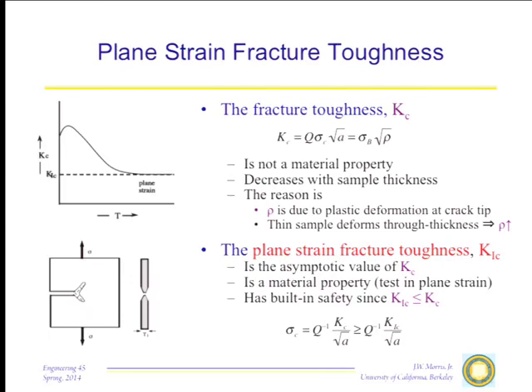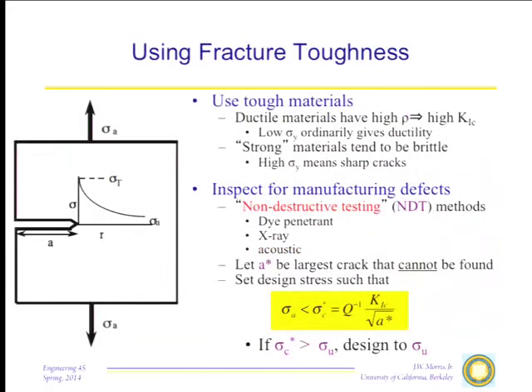So for most things, what you do is you find materials that are so tough that you don't have to worry about unstable crack propagation, because the design of the part is such that it's going to break in ultimate tension before a crack's going to propagate to failure. So an awful lot of things are designed so that sigma star is greater than sigma u, designed to sigma u. An awful lot of design is done that way. So what do you do if this gives you an unsatisfactory design?